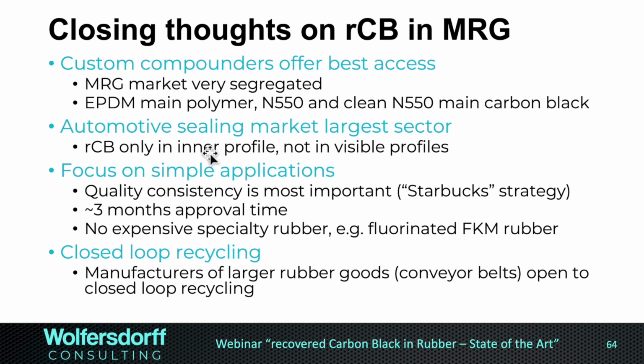Closing thoughts on recovered carbon black and mechanical rubber goods. So I think custom compounders like Clowit in the webinar offer the best access and the best way of a supply chain of sustainable material like recovered carbon black into the non-tire rubber market. Because the non-tire rubber market, the mechanical rubber good market, is very segregated, so there's so many applications, the volume might be quite small as well. EPDM is the main polymer, 550 and clean 550 are the main carbon blacks. Automotive sealing market is by far the biggest sector. Here only in the inner profile, not in the visible profile, is the opportunity for the recovered carbon black.